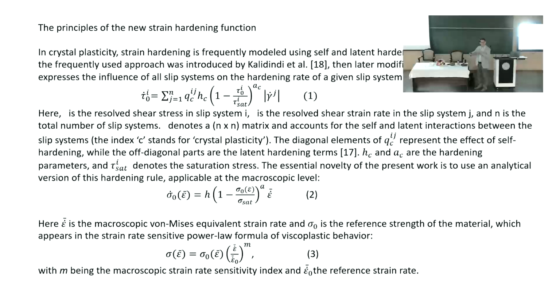There is a cross relation, self and latent hardening, expressed with a so-called matrix. Here this Q-C, C meaning crystal plasticity, I J, is a matrix describing with coefficients the possible interaction between one slip system and another.